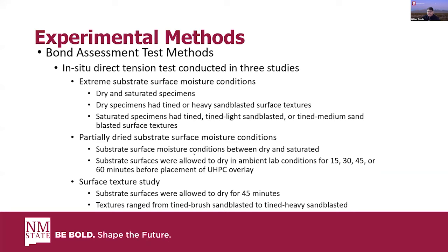And we also wanted to investigate the surface moisture conditions between dry and saturated. So we performed the partially dried substrate surface moisture condition. And here we allowed the specimens to dry in ambient lab conditions for 15, 30, 45, or 60 minutes before placement of the UHPC overlay. And it should be noted that the texture used for these specimens was a tined light sandblasted.